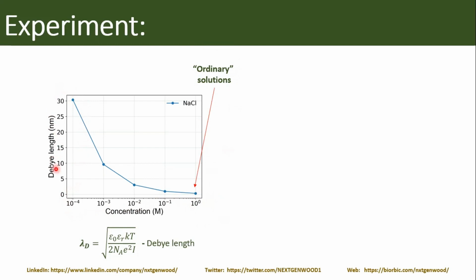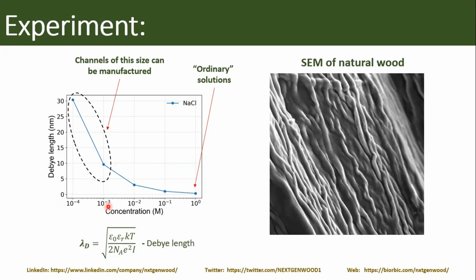So that's what we can do in lab. That's what we can find in nature. And for having such nanochannels and observing nano-confinement effect in them, we need to go to lower concentrations of electrolyte, something like 10 to the power of -3 or less than that. And so we were searching for a material which can give us lots of these nanochannels and which can be in the range of 10 to 30 nanometers.